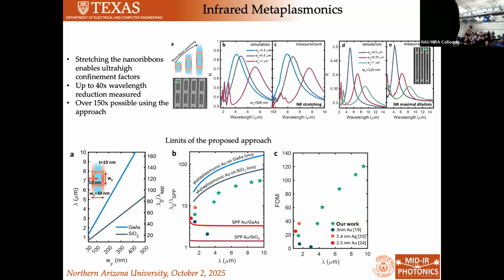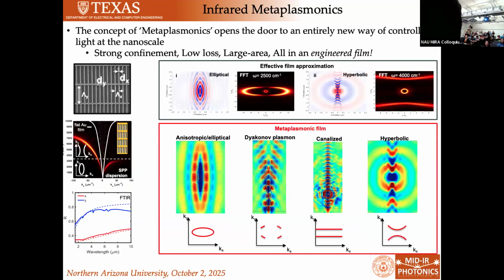And so our simulations suggest that for these metaplasmonic films on gallium arsenide, we can hit confinement factors of 100. So our wavelength can actually go to 100 with a free space wavelength. We have simulations that suggest that we can actually go a couple times higher if we use silver. And we can extend the operation. So this is the work that's been done using these atomically thin films, but our metaplasmonic films, we can bring those out all the way to the long-wave infrared because we're not fighting against that Landau damping effect. Now, there's one other thing that's really cool. This is my last slide.